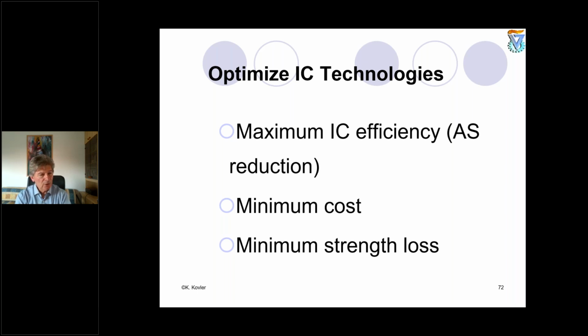And of course, we need to remember about the strengths, because if you introduce any internal curing agent which is porous, it doesn't matter, superabsorbent polymer or lightweight aggregate, we expect a strength reduction, because of the porous materials. It depends, of course, on the concentration of the porous materials inside concrete. And this strength loss should be minimized.